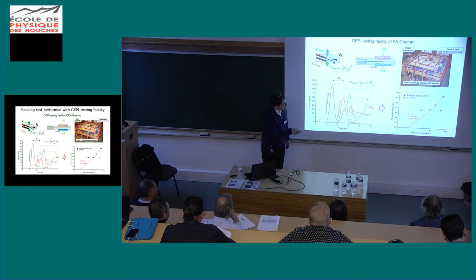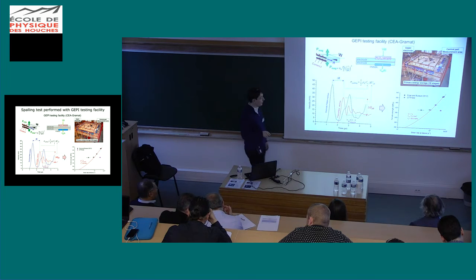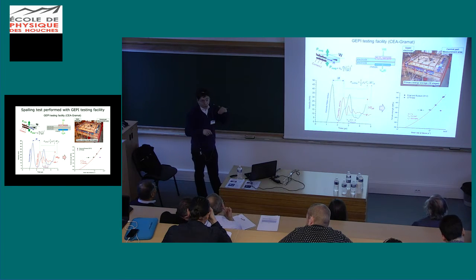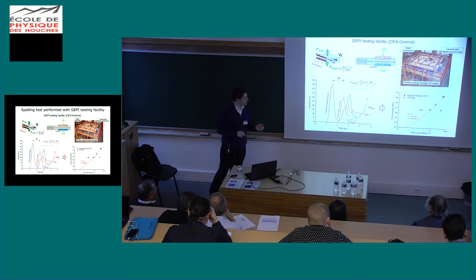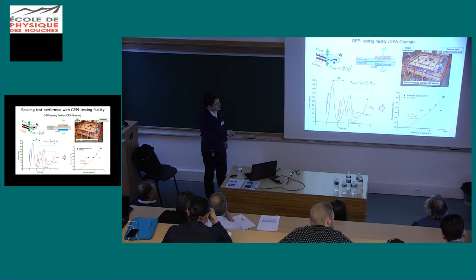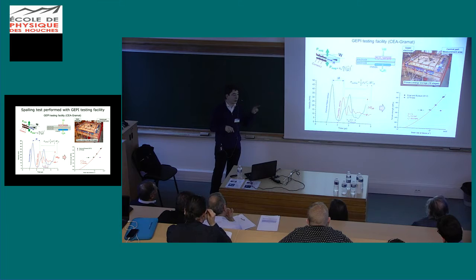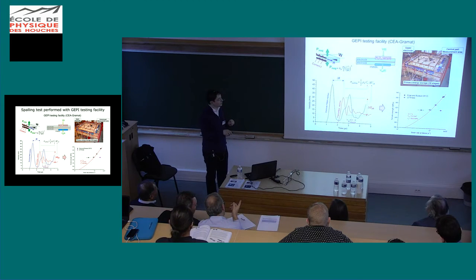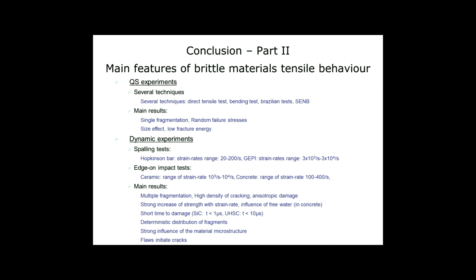Also, what was interesting to observe is that this point, in fact, corresponds to a test performed with a compression stress above what is called the Hugoniot elastic limit, so the elastic limit in uniaxial strain of the material. So you can observe that now the strength is much lower. So there is a possible coupling between compression damage and tensile damage. Okay, so it's important to prevent compression damage if you want to characterize the tensile damage of the virgin material. Okay, this is just a remark.